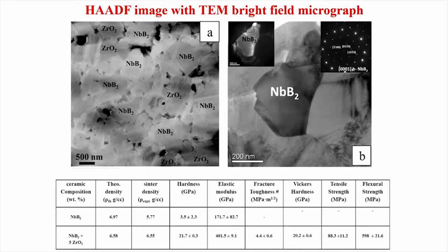So, this is that HAADF image, the high angle annular dark field images, and the TEM bright field micrograph. What you see here is the presence of niobium boride, and the zirconia phase is dispersed in the matrix, and there are equiaxed grains of niobium boride, which, if you look at this micron bar, are roughly around 1 micron in size. So, 1 micron or less than 1 micron, and this is the selected area diffraction pattern of the hexagonal niobium boride, where it is very clear that niobium boride is retained along with zirconia.